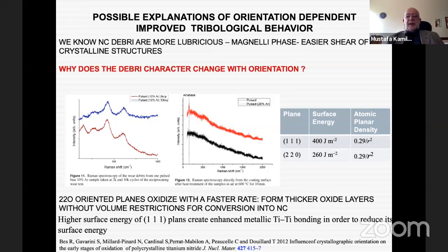So why is the question to be answered. That means when you reach a nanocrystalline nature, the volume of the oxide that is produced on the surface should be enough for the conversion of these structures into a crystalline phase. And since these are defective, we can end up with the formation of lubricious Magneli phases that show easier shear. When we looked at the literature with respect to oxidation behavior of these materials, we found an interesting study which mentioned that the 1-1-1 oriented planes are more oxidation resistant than 2-2-0 oriented planes. So this enlightened us in a way.